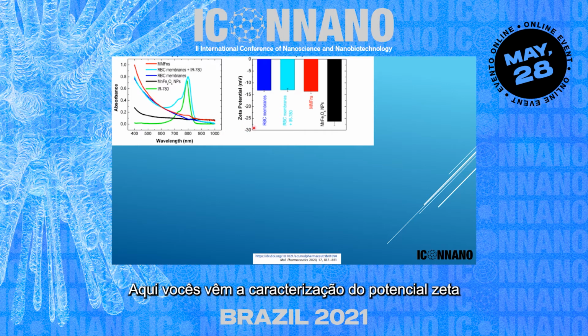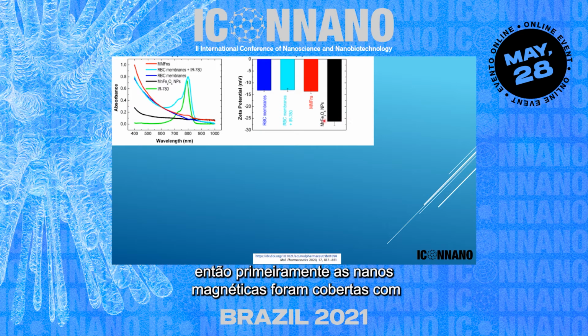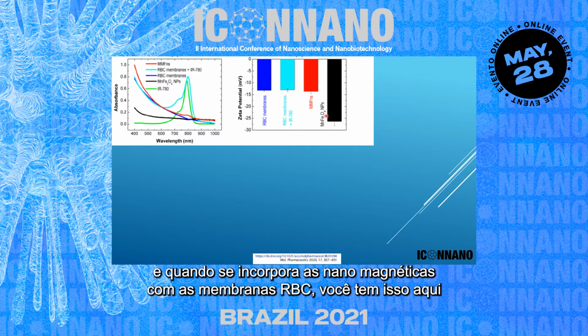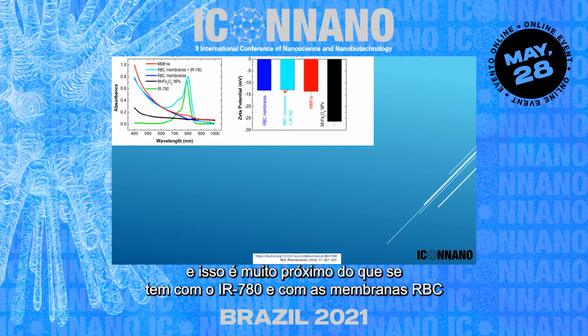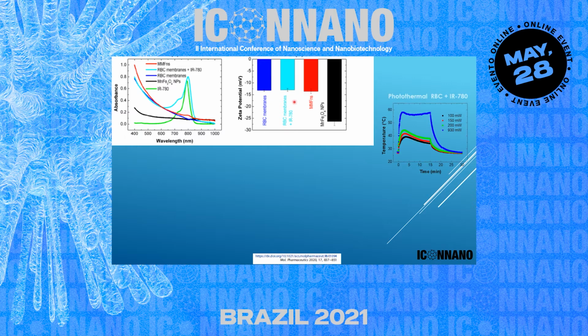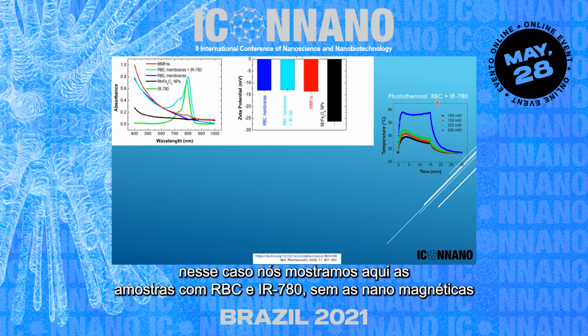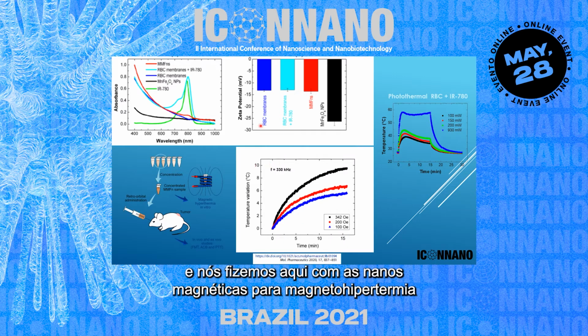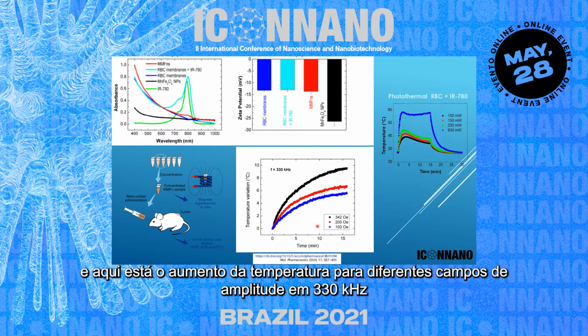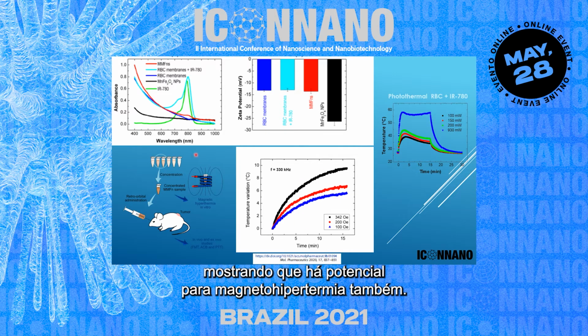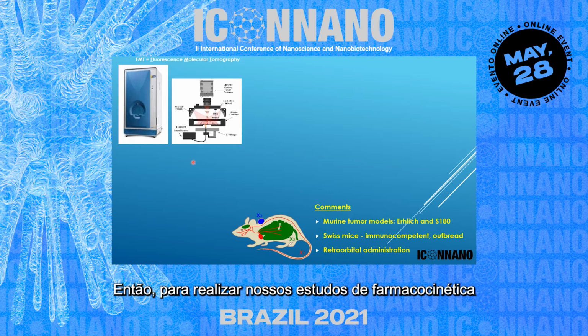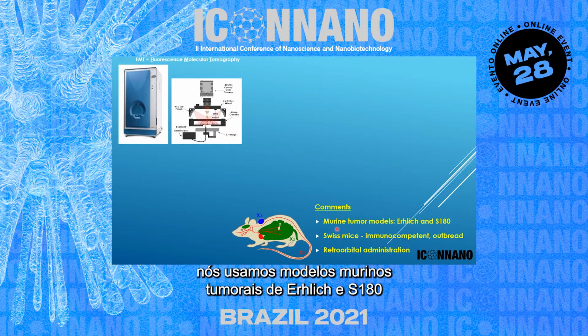Here you see the characterization with the zeta potential. First, the magnetic nanoparticles were citrate coated, and when you incorporate them into RBC membranes, you get this curve here. And this is very close to what you have together with IR 780 and the RBC membranes, as expected. We also performed photothermal analysis. In this case here, we are just showing the ones of the sample with RBC and IR 780 without the magnetic nanoparticles. And we did one with our samples with the magnetic nanoparticles for magnetic hyperthermia. And this is the increase of temperature for different field amplitudes at 330 kilohertz, showing that there is potential for magnetic hyperthermia too.